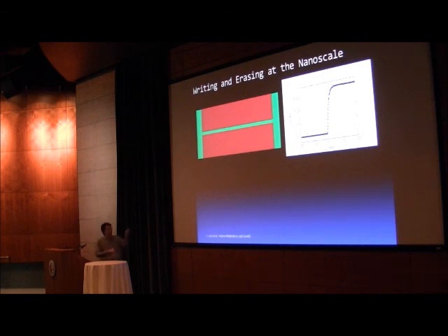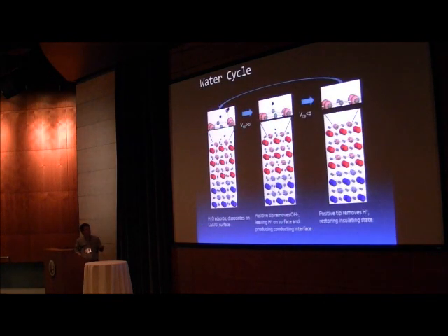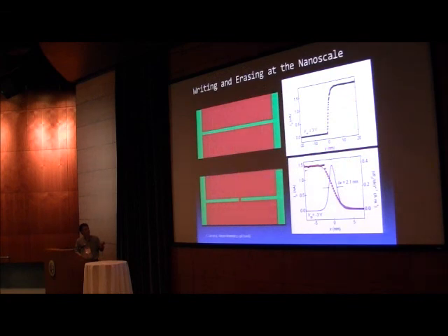So then if we want to know how wide this wire is, for example, what we can do is move across with a negative voltage. And when we do that, we can also monitor the conductance, and we see that there's a very sharp drop. And we can analyze the shape of that drop, and to our surprise, that is a lot sharper than what we expected. In fact, this data corresponds to a wire that was about 2 nanometers wide.